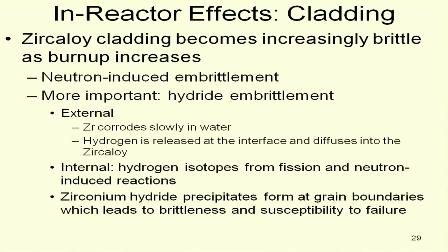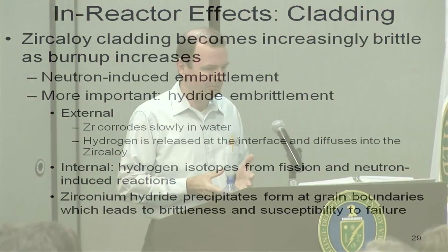This is fuel clad. As the radiation continues, Zircaloy cladding becomes increasingly brittle with burnup. It's not so bad when you're at power because it's fairly warm, and at that temperature the Zircaloy is reasonably ductile, but at that temperature it can have a tendency to sort of collapse onto the fuel pellets. When you cool off and get to room temperatures, then the brittleness can become more of a problem and is more pronounced because you get into the brittle temperature range.